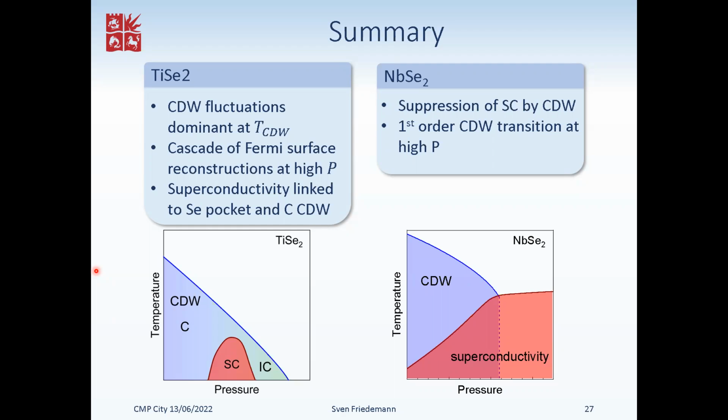What's going on in titanium diselenide? Because it's not at the critical point, it's somewhere in the middle. Why should the phonons or the fluctuations switch on at that particular pressure near the end? For BCS superconductivity, the electron phonon function doesn't necessarily want just the lowest energy phonons. In fact, some of the lowest energy phonons can act pair breaking.